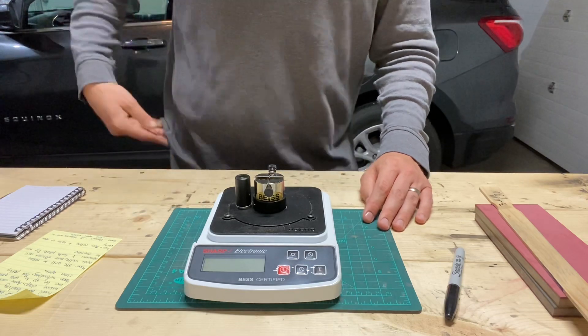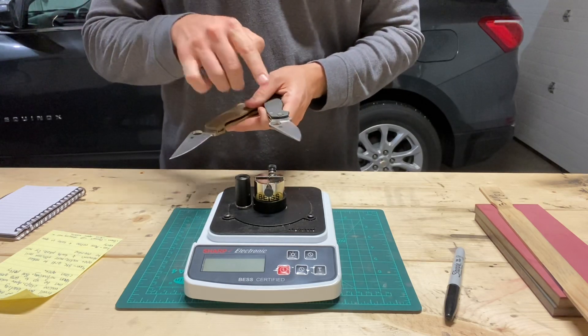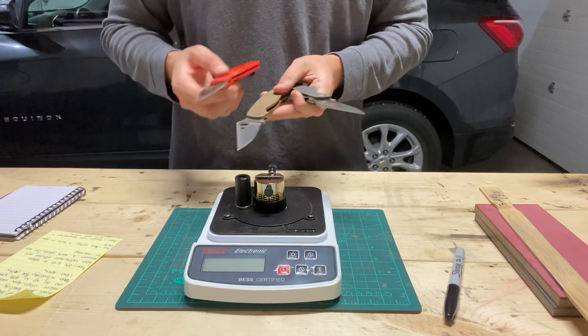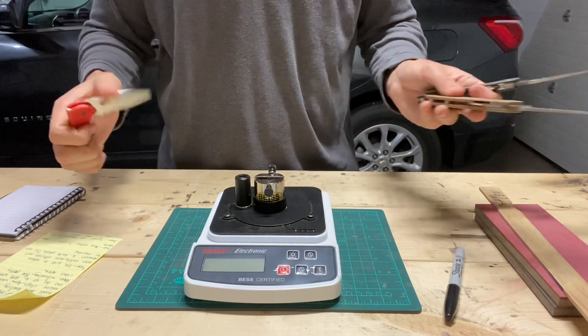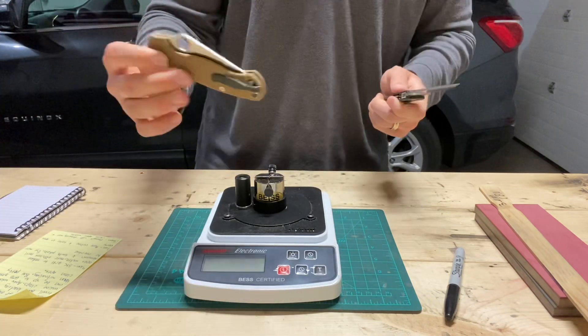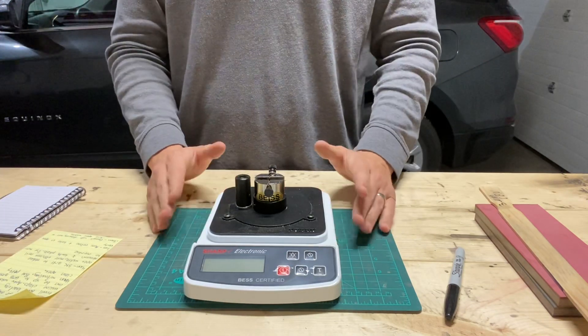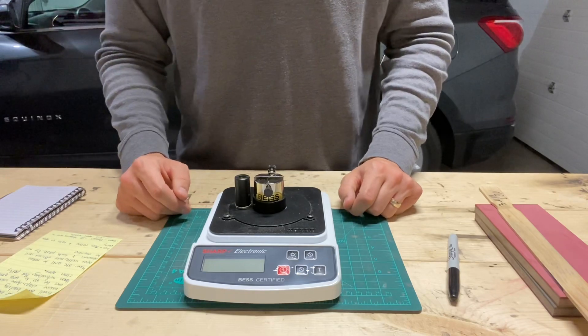There's a lot of experimentation still to do on different steels. Harder, more brittle steels work a burr differently — I'd expect the 10V to react differently than M4. M4 holds a temperamental burr way more than 10V. And something like LC200N, which is significantly more malleable and tough, will be different yet. According to the book, the more malleable the steel, the more necessary that high-grit deburring pass is, whereas harder, more brittle steels don't necessarily need it. Anyway, that's a pretty long video — I hope it made sense. Thanks for watching.